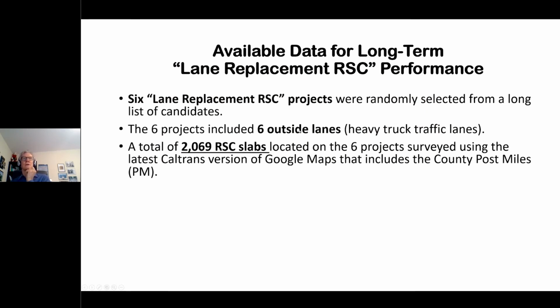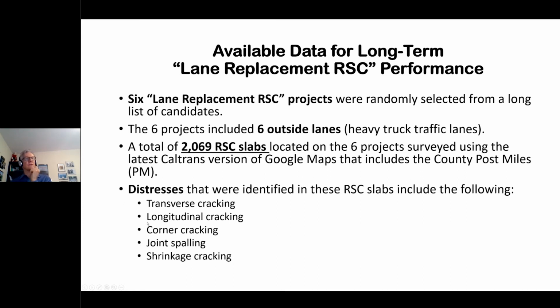Okay, we picked 6 of these projects from a long list of candidates. These were all in the outside lane, so note that here. Whereas prior, some of the individual slabs were in the inner lane, some were in the outer lane. But these are all in the heavy truck lane. There just weren't any complete replacements done in the inner lanes for obvious reasons. There was not enough cracking. This included a total of around 2,000 slabs. And we used, again, the latest version of the Caltrans Google Maps. And the distresses that we found were basically identical to what we found on the individual slabs. Transverse cracking, some longitudinal, some corners, some joint, and a little bit of shrinkage cracking.